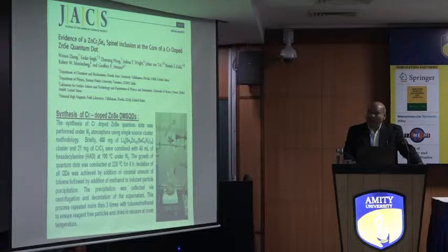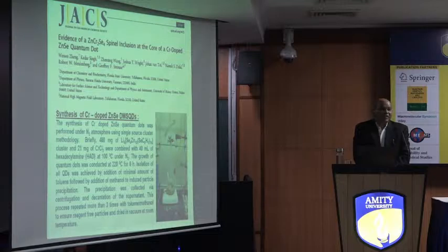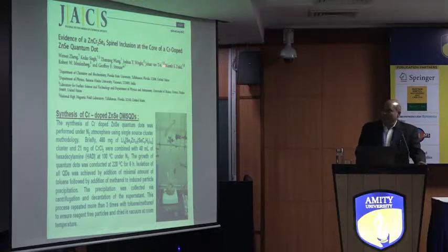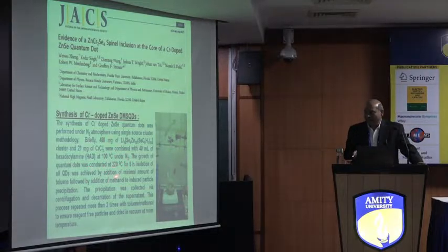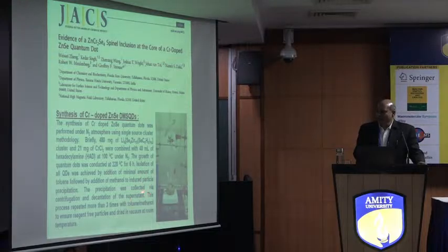But I just want to show you my work, from when I was in the US. This is the work on chromium-doped ZnSe quantum dots. Here we find that ZnCr2Se4 is an inclusion in ZnSe. But how can we synthesize it? This is a solvothermal method. Here we take a Zn10 cluster, and chromium chloride as the source of chromium. Then we conduct the reaction in a nitrogen environment up to 220 degrees centigrade. Then we did some purification.